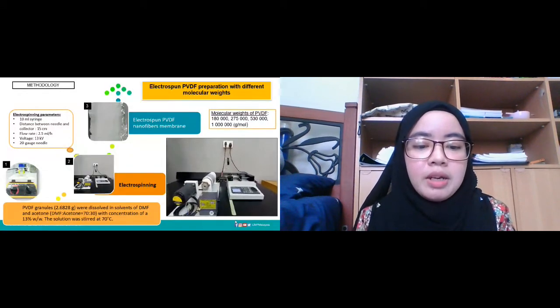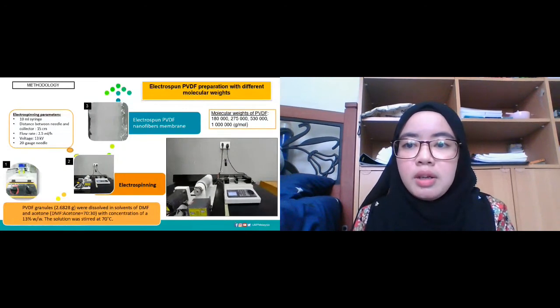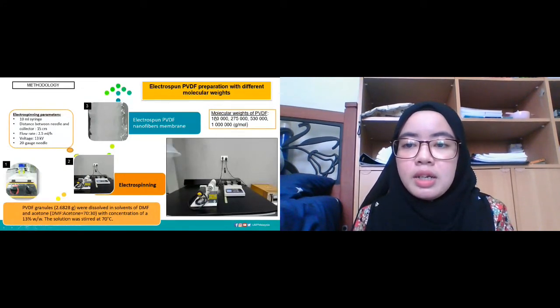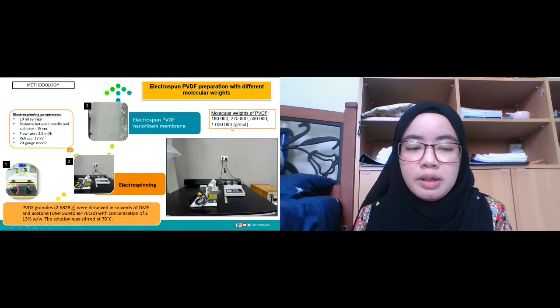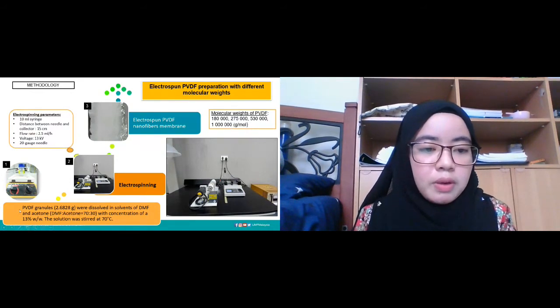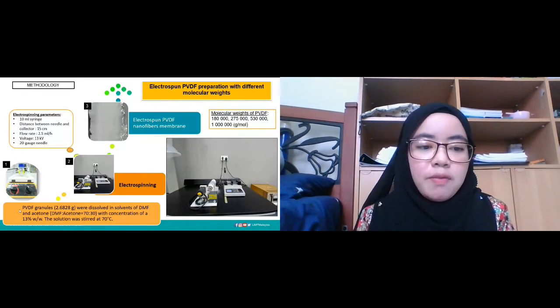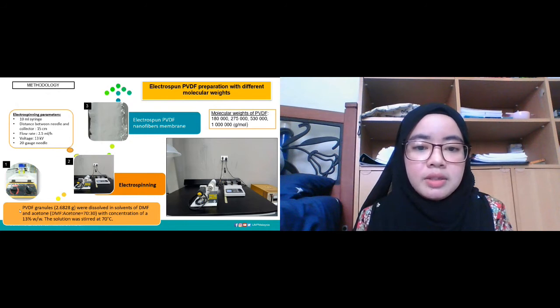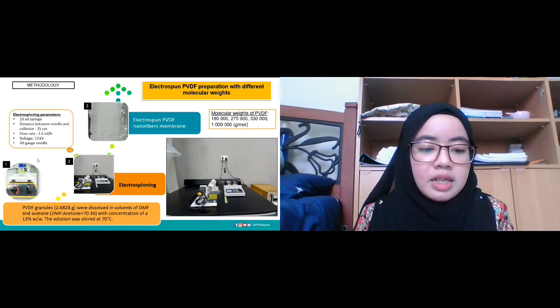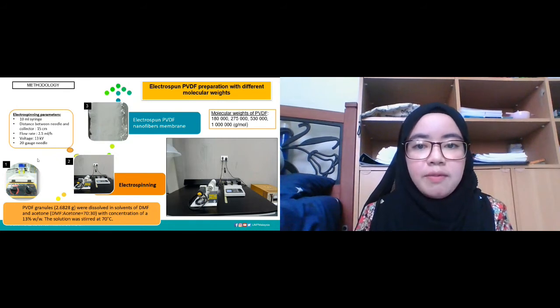Next, in this work, we prepared PVDF with 4 different molecular weights. We use 4 types, which are 180,000, 275,000, 330,000, and 1 million grams per mole. First of all, we dissolve PVDF into a mixed solvent of DMF and acetone. DMF stands for dimethylformamide. The solution was stirred for 12 hours at 60 degrees Celsius. Then 10 ml of PVDF solution was placed into the syringe to produce the nanofiber membrane by electrospinning. Lastly, the third image shows the end product of electrospinning, called the electrospun PVDF nanofiber membrane.